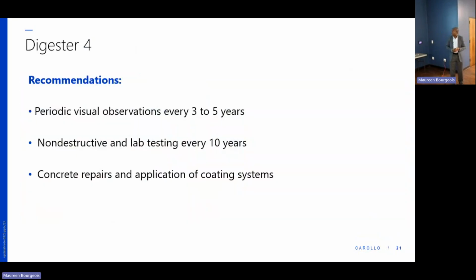So what is our recommendation also for digester number 4? Again, the same thing, periodic visual observation every 3 to 5 years, monitor just like we did and see if anything changes. And then we have also recommended non-destructive or lab testing every 10 years to see if the situation deteriorates from the benchmark that we have today. And then for those areas where we have the localized spalling, the reinforcing being exposed, we recommend concrete repairs and application of a coating system, at least on the areas where the paste has been eroded, the surface of the concrete has been eroded. And we recommend that work to take place in the next 3 to 5 years.